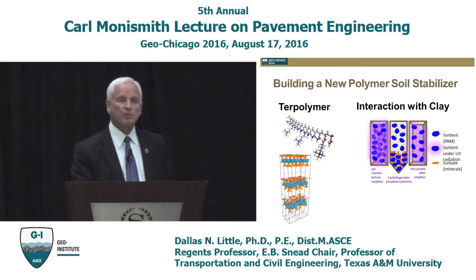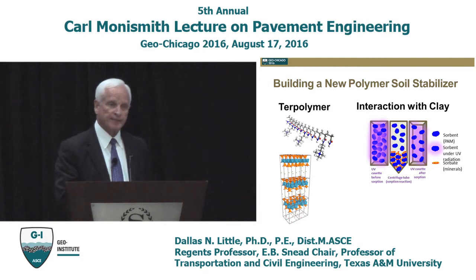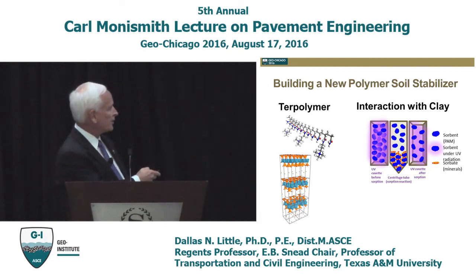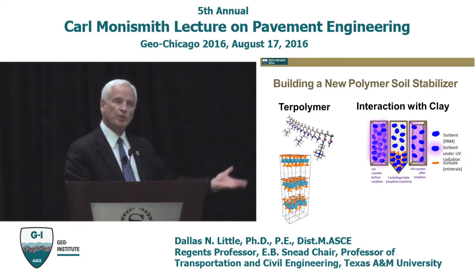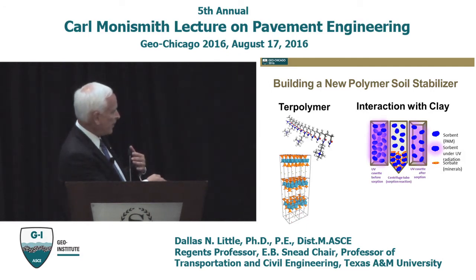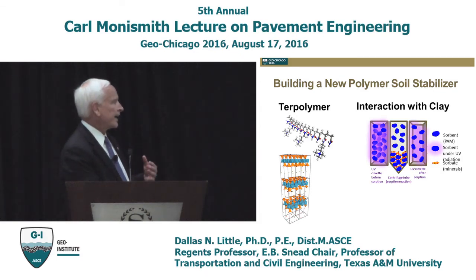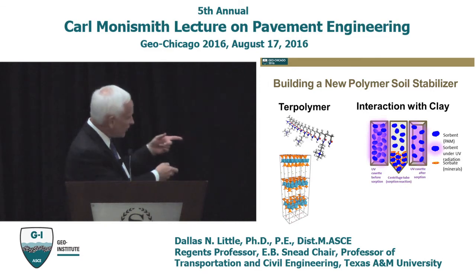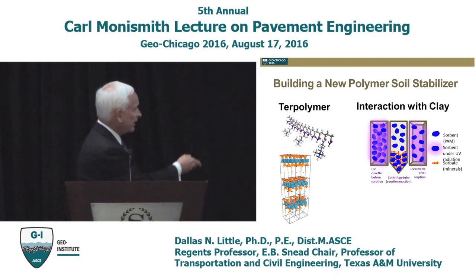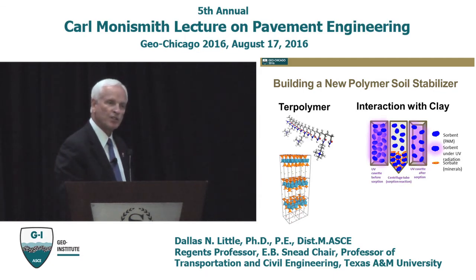One of the other compounds that we've been looking at is a terpolymer to stabilize soils. Now, terpolymer is a polyacrylamide base with an additive that has a cationic, an anionic, and a non-ionic component to it, thinking that those components will be able to interface with some part of the clay molecule, and hopefully the molecule is small enough to meander through into this interface between the clays. You can see the smectite type layer here, to meander in there and interconnect at those activation sites and stabilize the clay.